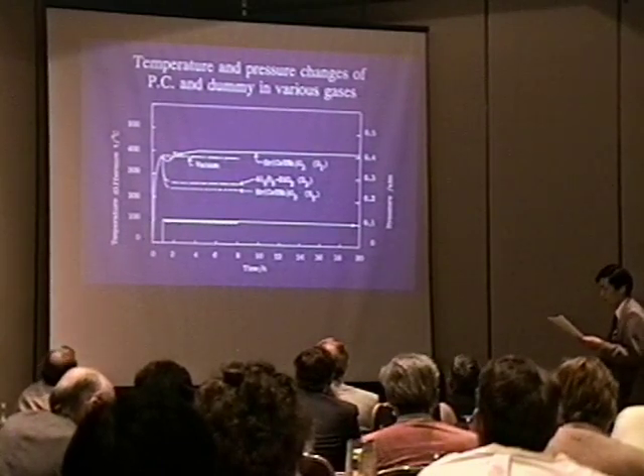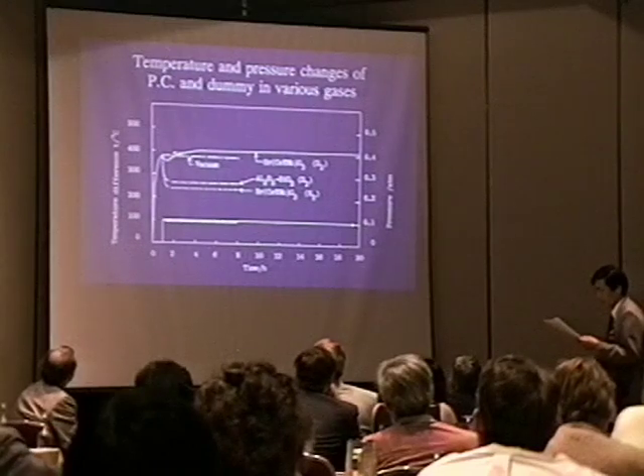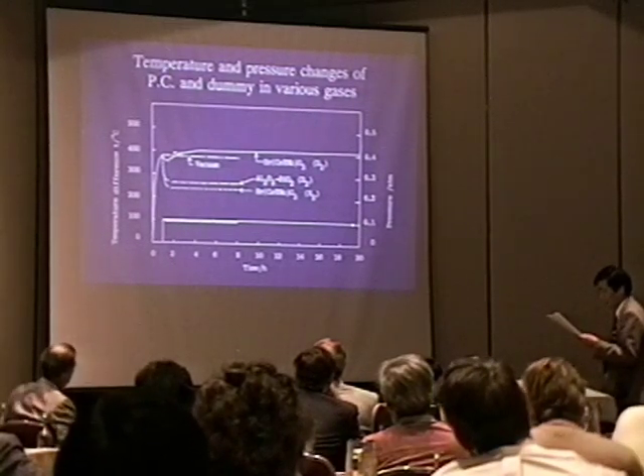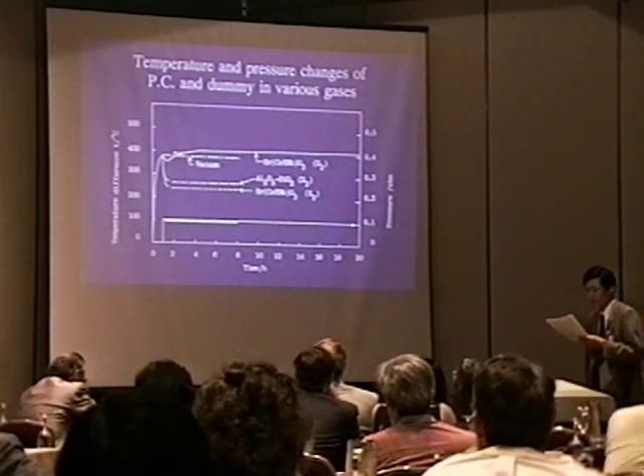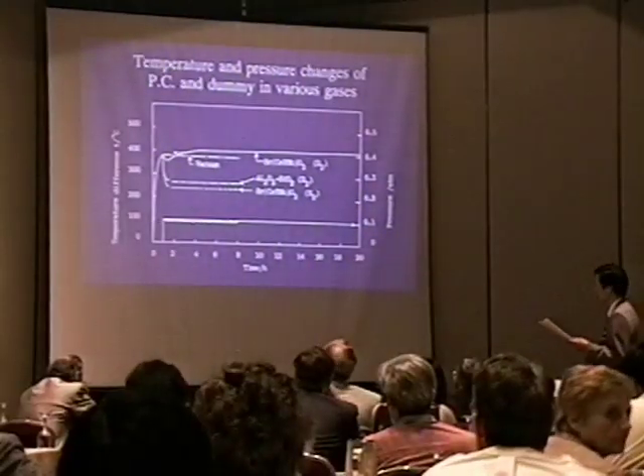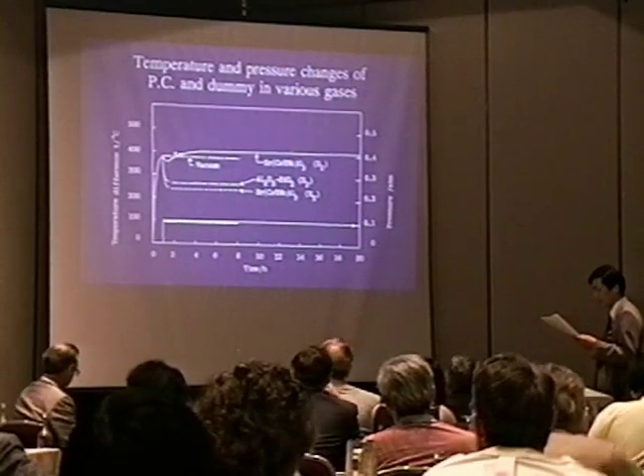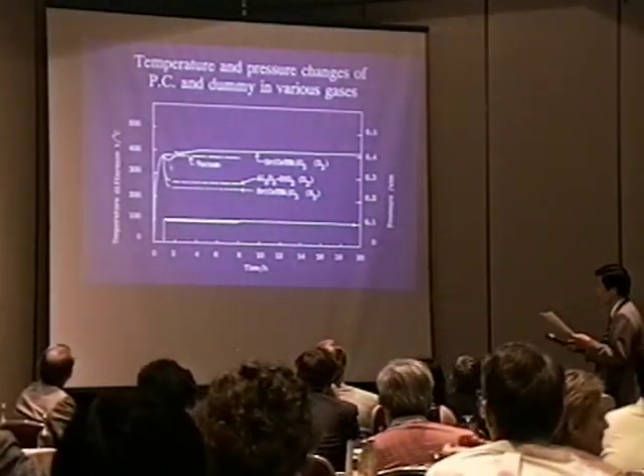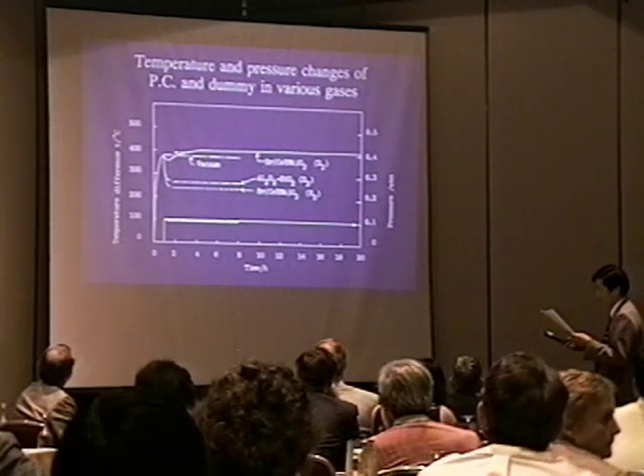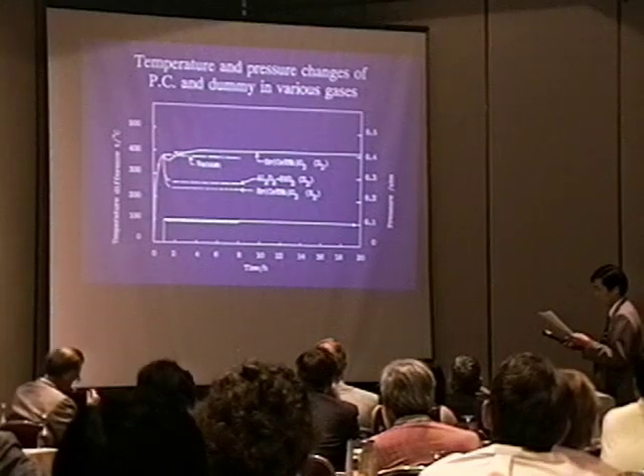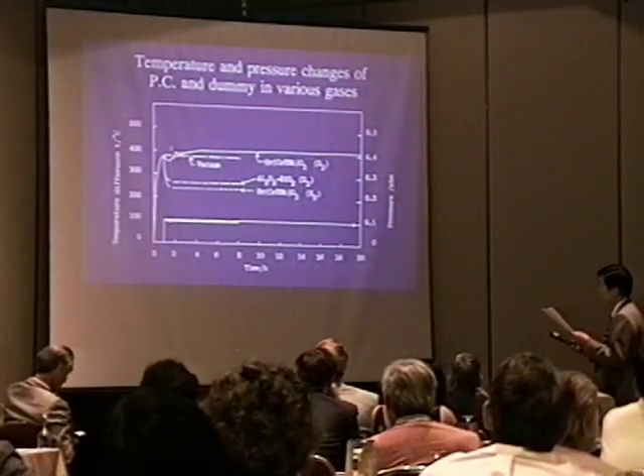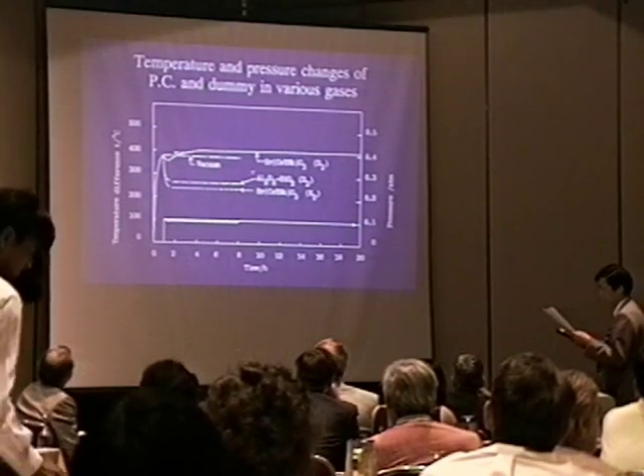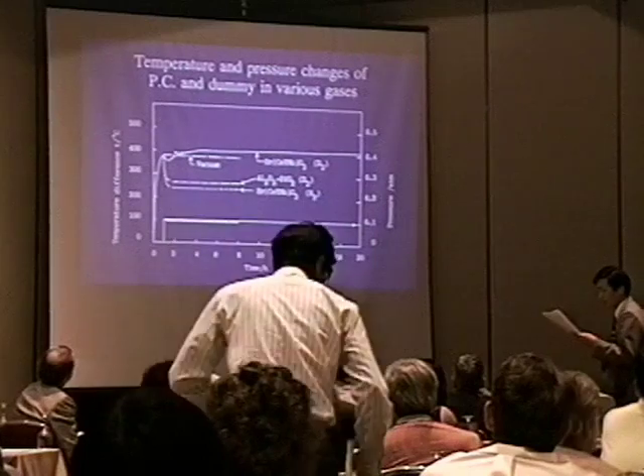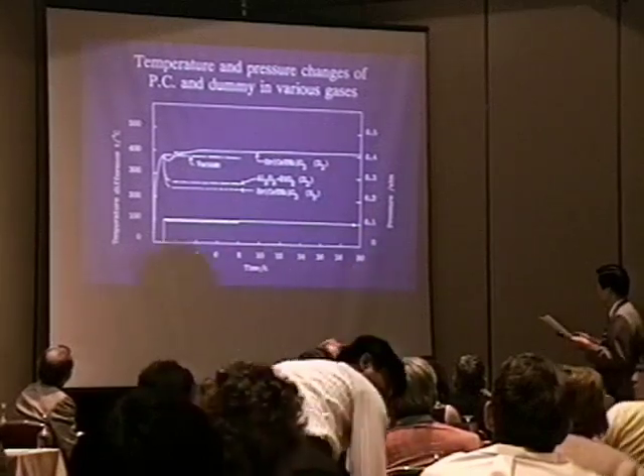And this shows temperature changes of the proton conductor sample and the dummy sample. They are placed in the atmosphere of deuterium or hydrogen gas. The samples are heated by 50 watts up to a constant 380 degrees centigrade within 1 hour. The deuterium gas was then introduced into the reaction vessel, and temperature fell to around 350 degrees centigrade, but it again started to rise, reaching up to 400 degrees centigrade after 5 hours. And this temperature was maintained for at least 20 hours.